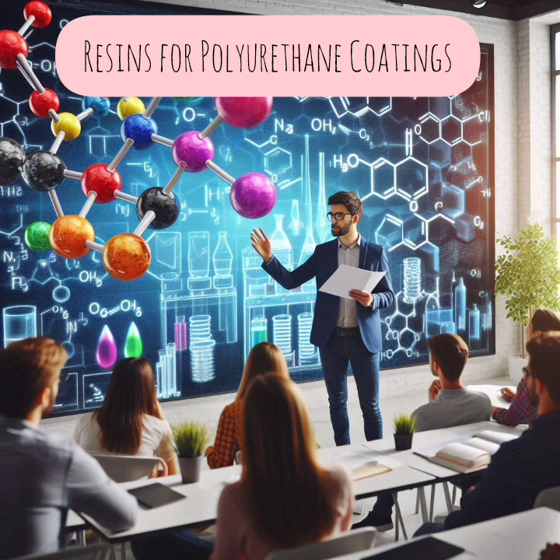to make isocyanate-terminated prepolymers. In these two-pack systems, pigments and additives are dispersed in the hydroxy-functional polyol resin and given as component I or A. Component II or B is the hardener containing the isocyanate adduct as described above. These are mixed at the time of application as per the ratio given by the manufacturer, and the resultant ambient-cured film, like epoxies, is a tough one, resistant to solvents, many chemicals and corrosion.